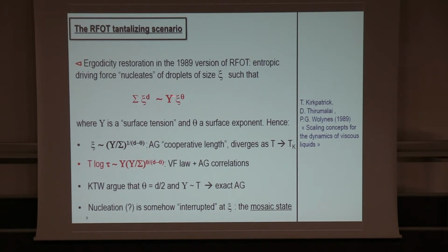If you assume that barriers scale like either of these terms, which are actually the same, then T log tau is going to grow like this. And this gives back a super-Arrhenius Vogel-Fulcher type of law, and these Adam-Gibbs correlations between thermodynamics and dynamics that I talked about. And in this paper, KTW argue that theta should be d/2 and that Upsilon should be proportional to temperature. And in this case, actually, you get not only Adam-Gibbs phenomenology, but you get actually an exact Adam-Gibbs relation between log tau and 1/s.